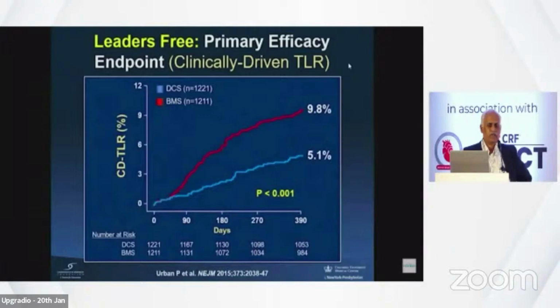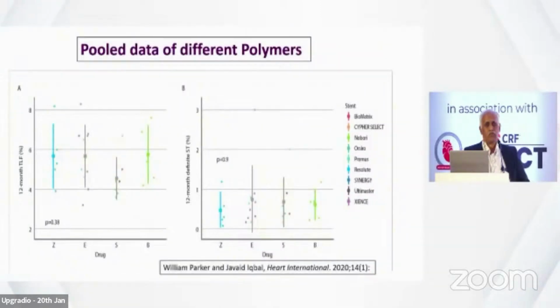We do a polymer-free stent, and there is no polymer. This is because in high bleeding risk patients, you don't want to give anticoagulants for a long time. So remove the polymer and give short-duration dual antiplatelets. It is superior to the bare metal stent, but it's not superior to the biocompatible polymers. The pooled data of different polymers doesn't show any difference in the efficacy endpoints.